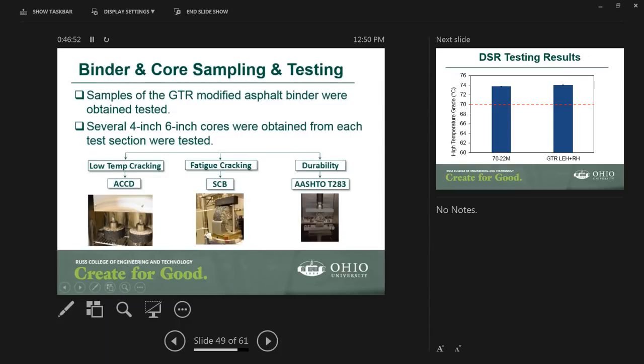So we obtained, the same way that we did with the Columbus test section, the binder at the terminal as well as from the production line at the asphalt plant. And then in here, we had several cores. We obtained 4-inch and 6-inch samples along the test sections.